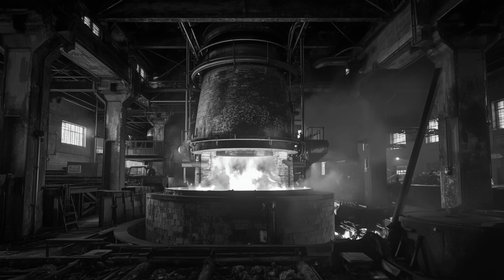The brickwork wants to shrink. The iron bands resist that shrinkage, holding the structure in place with immense tensile force. But the brickwork is also trying to expand thermally. Hot materials push outward. The iron bands constrain that expansion too, creating a compressive stress within the brick. The result is a complex balance. Thermal expansion pushing out, volumetric shrinkage pulling in, iron bands resisting both, all happening simultaneously under sustained heat.